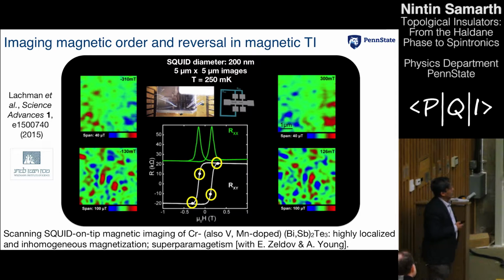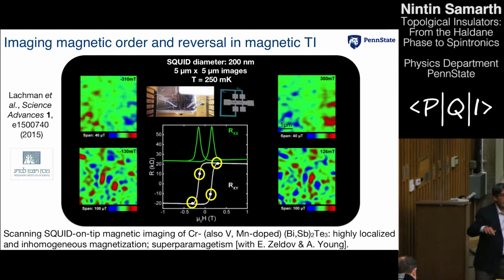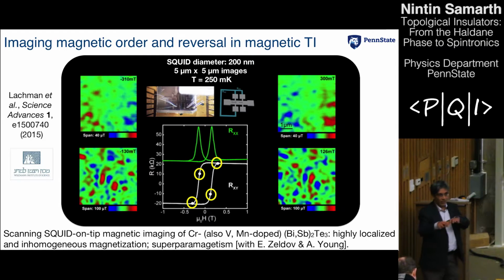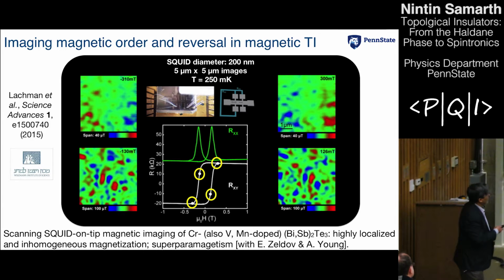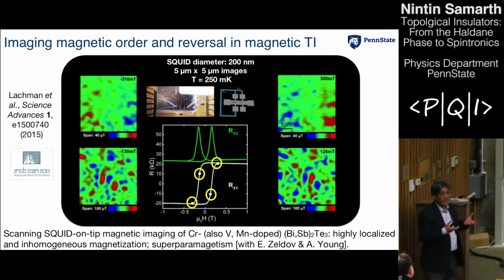Now, what his SQUID measures is variations in magnetization. So he's seeing the fringe fields that are created by inhomogeneous magnetization in your sample. So if you have domains, for example, you'll see the magnetic domain. So let's start at this end over here in the hysteresis loop, and this is the kind of image he gets. Okay? Now, you go over here where the magnetization is just starting to switch, and you start seeing that red and blue regions are opposite directions of magnetization. You start seeing that this magnetization is starting to switch.